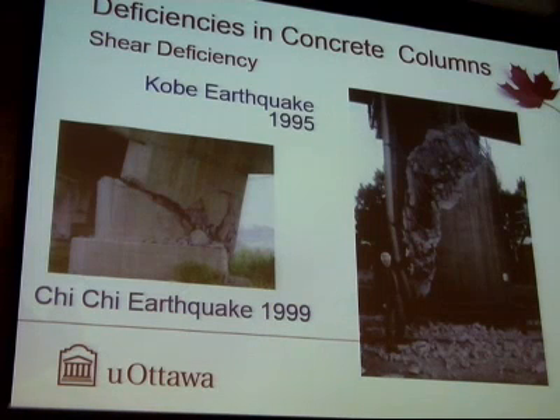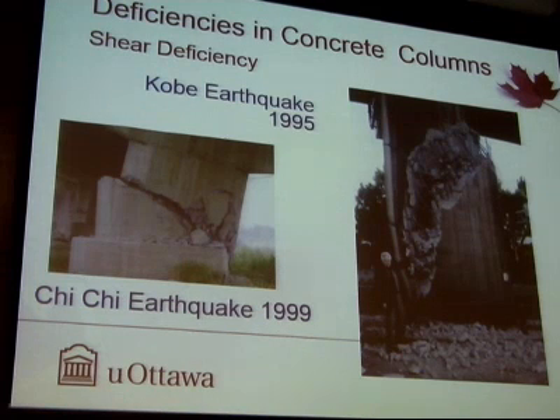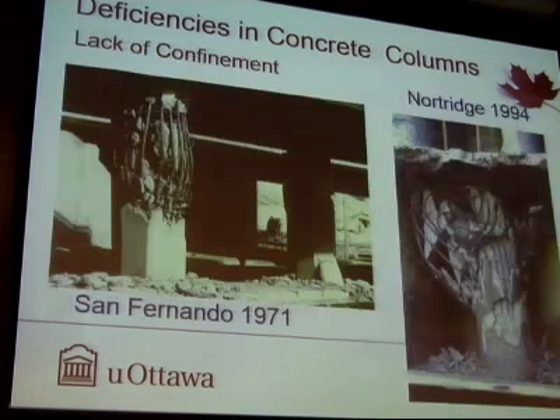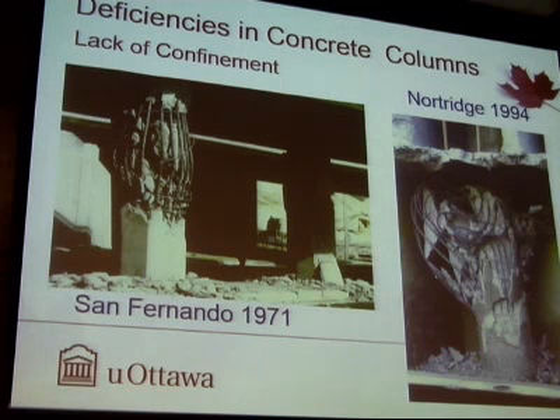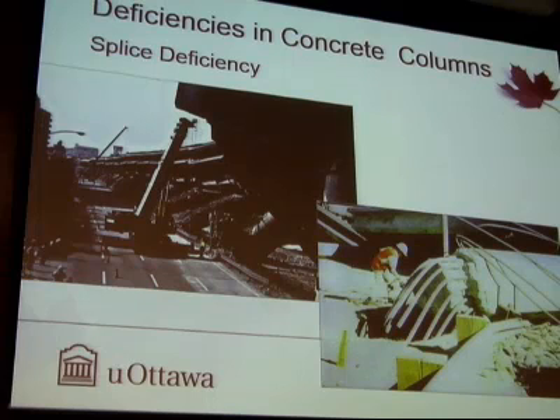And typically columns suffer damage due to lack of transverse reinforcement. Here you see not enough transverse reinforcement and hence not enough diagonal tension capacity. If you do not have sufficient transverse reinforcement, especially in highly axially loaded columns, then of course you do not have the ductility that you wish to have in concrete, and lack of confinement provides another deficiency. And thirdly, lack of sufficient longitudinal reinforcement splicing causes a problem. In the old practice of bridges, we would reduce lap splice lengths as low as 20 times bar diameter. And these happen to be in potential plastic hinge regions, obviously creating problems.